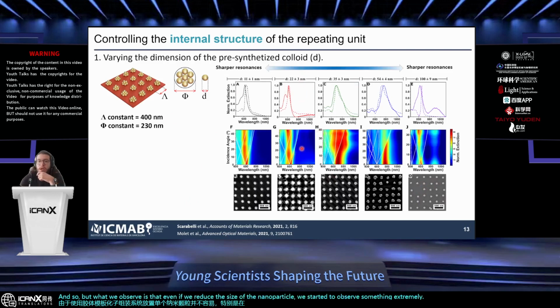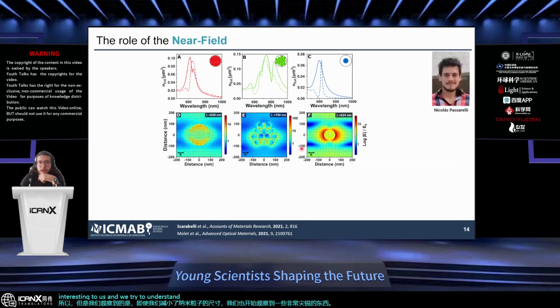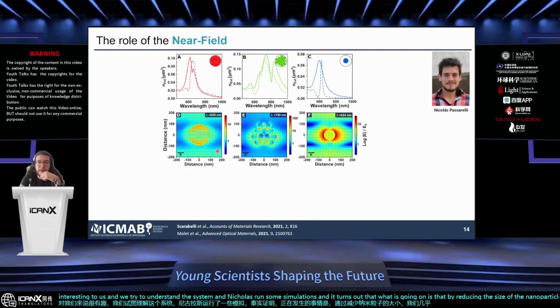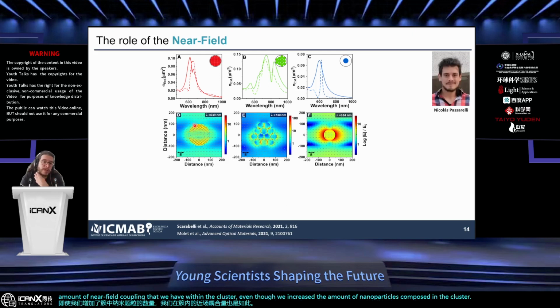And this was interesting to us, and we tried to understand the system. And Nicholas ran some simulations, and it turns out that by reducing the size of the nanoparticle, we pretty much reduce the amount of near-field coupling that we have within the cluster, even though we increase the amount of nanoparticles composing the cluster, the repeating unit. And this is due to the fact that the interparticle distance compared to the size of the particle will increase.